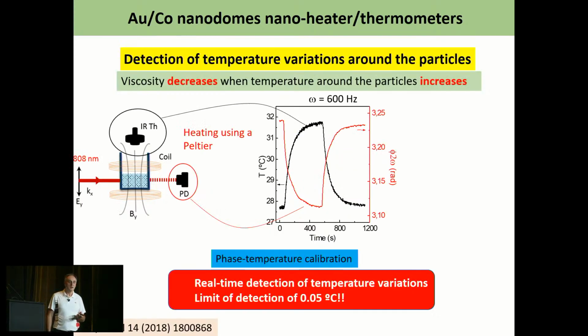So since the viscosity decreases with temperature, we can use this change of phase lag, which is because of viscosity, to measure the temperature by calibrating the system. And that's what I did here. We have our system I showed you before.